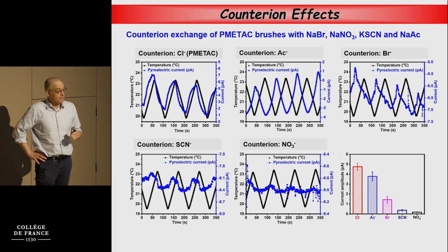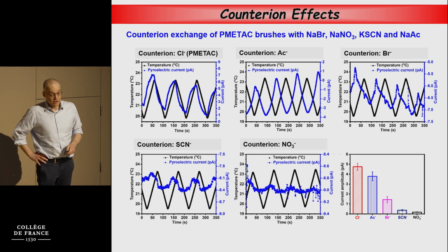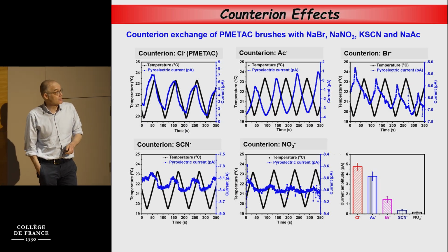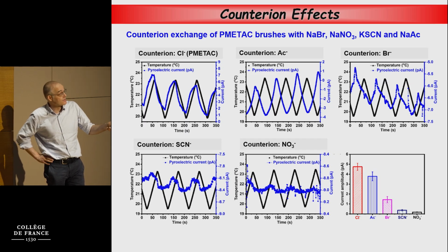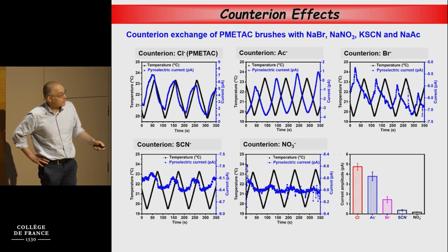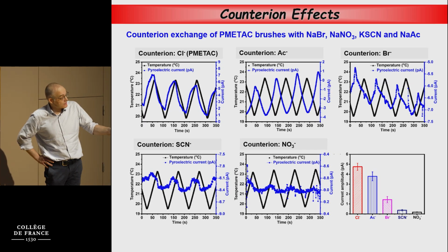Then we did a number of experiments to try to get some more insight as to what drives these observations. An obvious thing to do if you work with electrolytes is to change counter ions. So we changed the chloride counter ions of these strong electrolytes with bromide, nitrate, thiocyanate, and acetate. And the interesting observation is that the type of counter ion affects the pyroelectric current that we measure.